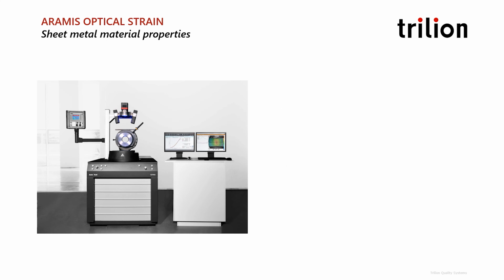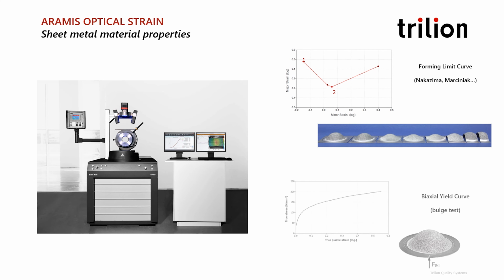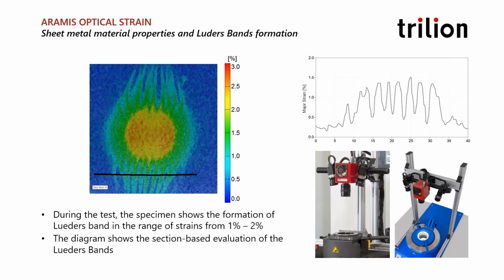The severe forming that takes place in production cannot be understood through uniaxial testing. Biaxial dome testing, such as the Nakazima or bulge test, yield the material properties necessary to build sheet metal forming limit curves. The ARAMIS is mounted above the dome and shielded from the high pressure oil while the material is taken to failure over a series of tests.